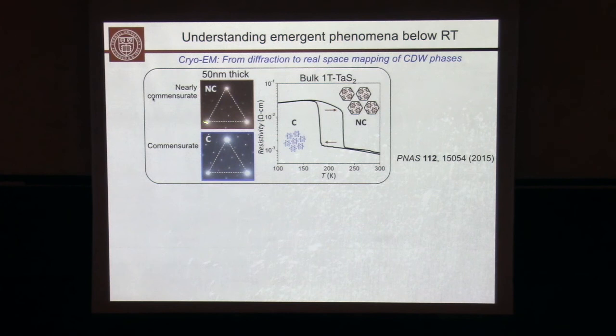Now, diffraction is powerful because these superlattice peaks, these dim peaks right in the center (the bright ones are the Bragg peaks), encode the order of that superstructure. And what you see right away, oh, you can't. Okay, so I've added these small little triangles, which you cannot see. You will see that the peaks change positions when you go to this commensurate state. But not only do these three peaks change, you also get additional peaks due to that new phase the system is in. So diffraction is certainly very interesting and very important in mapping phase transitions.